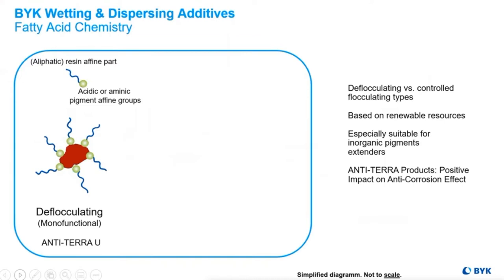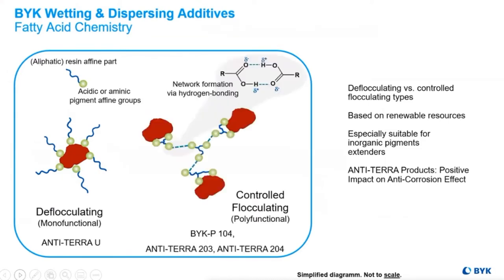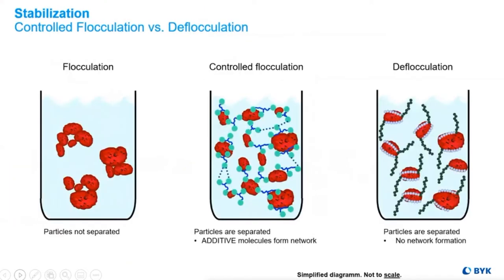They can be monofunctional with a pigment affine group and a lipophilic portion for steric stabilization. Or they can be polyfunctional with a hydrogen bonding formation to provide a network of controlled flocculation. It really is based on the stabilization choice of the formulator.